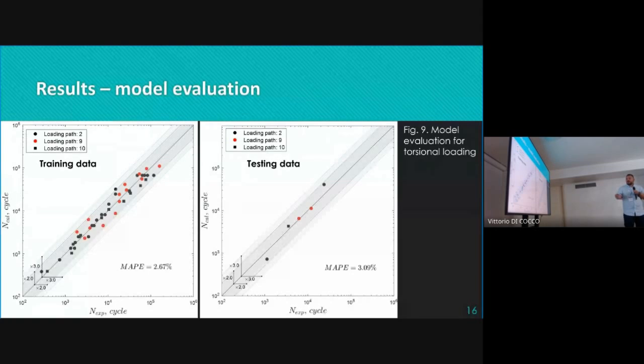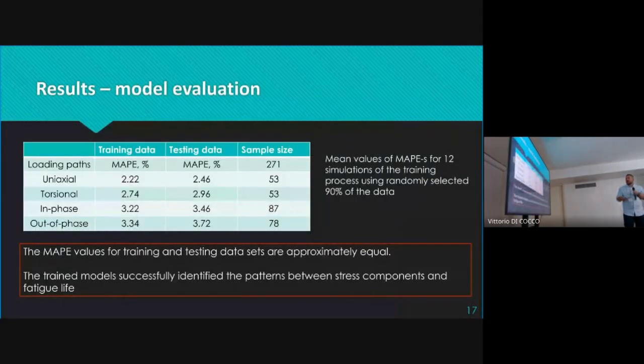Could you please? Oh, okay, never mind. So this is the mean value. I mean, it's a mean value of a mean value, because we did this process 12 times, and then we averaged all the MAPE values for those 12 times, and you can see them for the training data and the test data for all 4 sets. They're actually almost equal. I mean, there's no significant difference, especially for the testing data, when it was 1 or 2 specimens for the set that was not taken into the test. It has a bigger impact on the percentage, but they are all within the boundary. The model works very well with that.